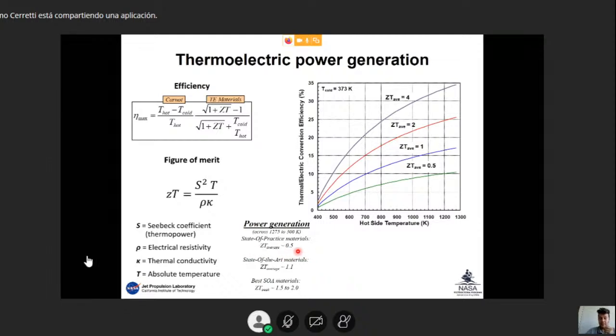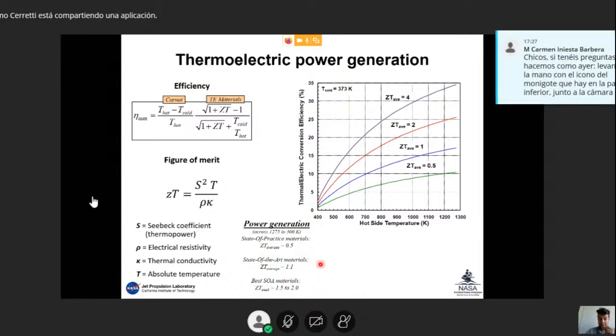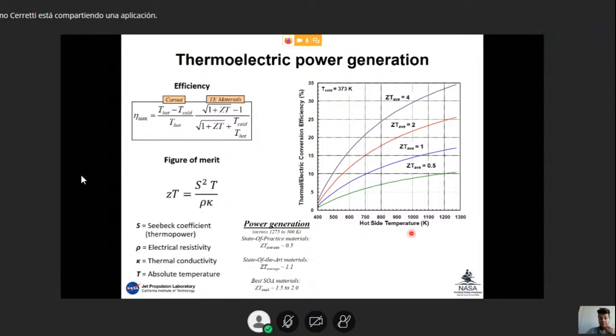The average ZT of the state-of-practice materials, so what was used in the previous RTG technologies, is about 0.5. The state-of-the-art materials nowadays have an average ZT of about 1.1, and the best state-of-the-art materials can achieve a peak, so maximum, ZT of about 1.5 to 2.